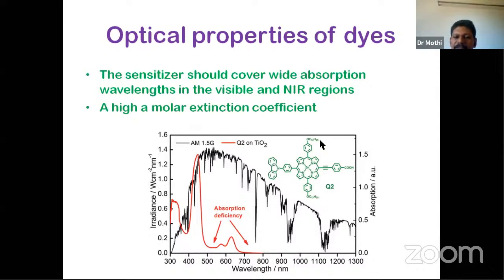Okay, so here we can see a structure of a dye which is porphyrin based, and the red line represents the absorption spectra of the porphyrin dye. The absorption spectra clearly shows that it has a strong absorption around 450 nanometers, and then some absorptions go up to 700 nanometers. So there is some absorption deficiency here. What we observe here is that the extinction coefficient of one band is very, very strong. So this dye has the capability to act as a solar cell dye.